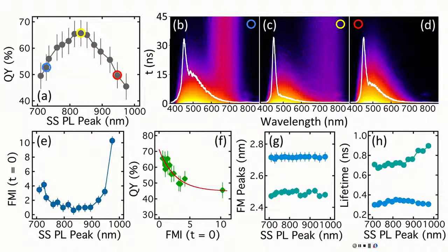Yeah, because you have the same correction to your bulk energy, right? The confinement correction depends only on the size of the crystal. It shifts by a constant, independent of the energy. Doesn't matter which transition you're looking at. Of course, in some approximation, you just apply this confinement correction.